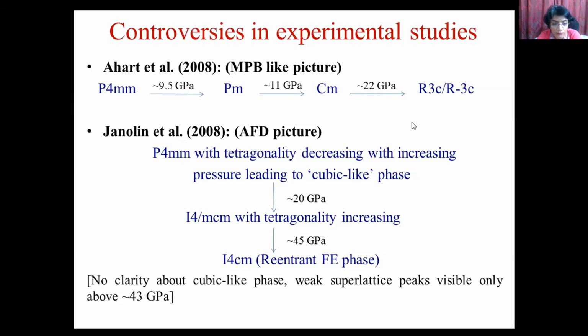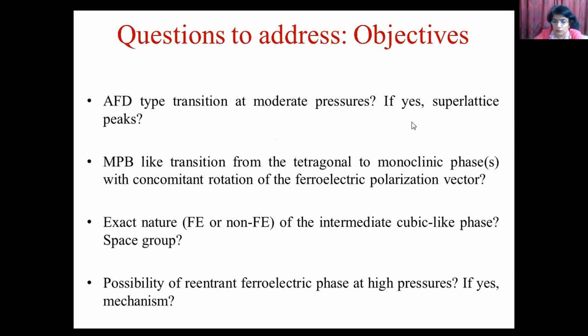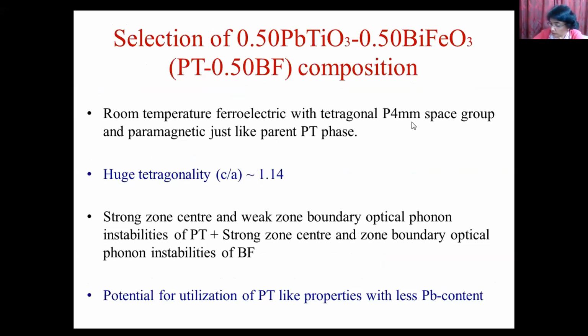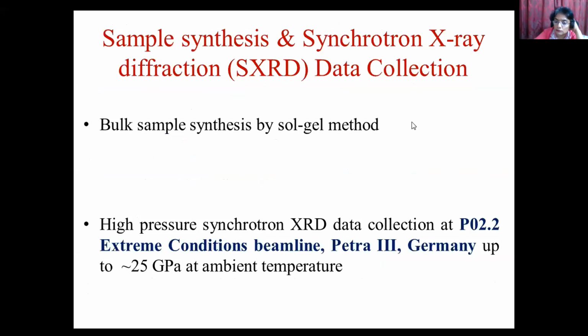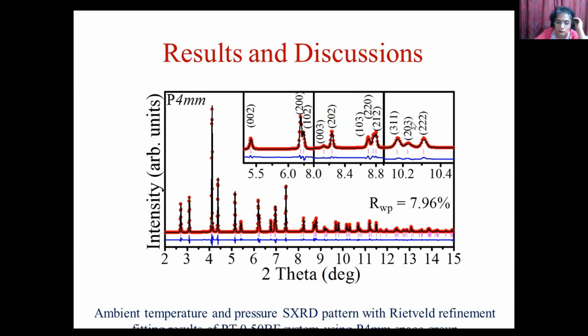Okay, and the second picture presents confirmation of the AFD picture. Now there are many questions which arise, like what is the exact nature of the transition, AFD or MPB? To address this issue, we have selected the bismuth ferrite lead titanate solid solution system, because bismuth ferrite has a strong zone boundary optical phonon instability, so it will enhance the intensity of any superlattice peaks, if there are any present. The data has been collected at the Petra 3 extreme conditions beamline.